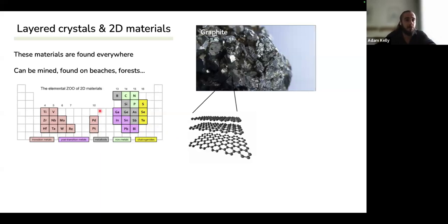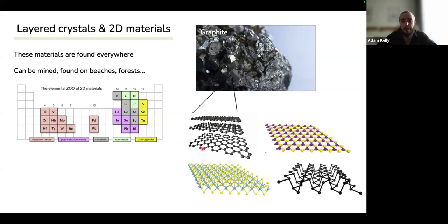So we can find these anywhere. We can synthesize them. We can mine them out of the ground. We can find them in beaches and forests. They come like a crystal, which when we look inside, they're often these 2D layers. So graphene is shown here, which is a hexagonal lattice. However, if we take something like boron and nitrogen and alternate the sites in this hexagonal structure, we'd have boron nitride, which is an insulator. We have MoS2, and also we have structures like phosphorene.